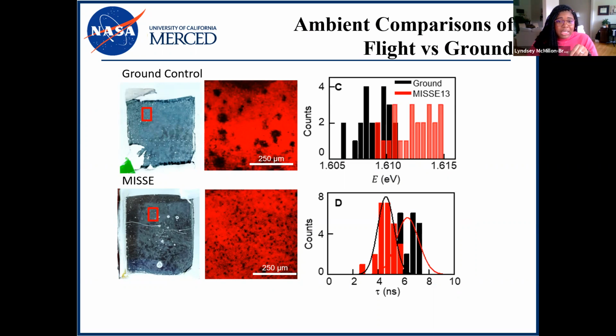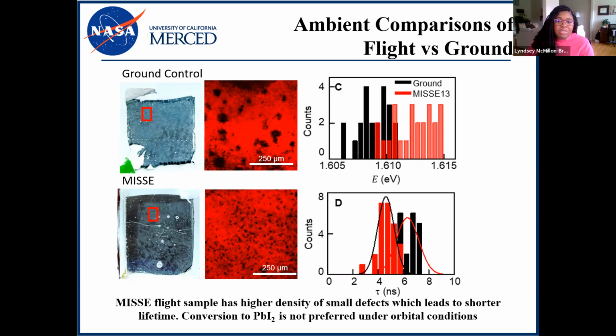And on panel C and D, we're looking at histograms generated from PL maps. So panel C is mapping the central emission peak energy in electron volts, and panel D is summarizing the charge recombination lifetime. So if we look at these, we see the MISSE sample overall has a higher energy and it's blue shifted, but the MISSE sample also has a slightly lower lifetime. So when we take this data together, we summarize that the MISSE sample has a higher density of small defects, which explains why the lifetime is a little bit shorter than the ground control, but the energy blue shift is typically indicative of dissociation into methylammonium and lead iodide, but we don't see any lead iodide forming in the film. So at this point, we're still unsure entirely where this blue shift that we're observing is coming from.